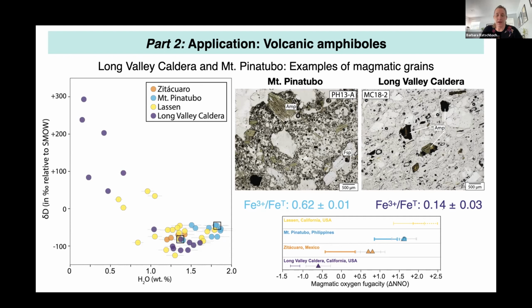So now when we, again, collect spectra, find a model, and get ferric overtone ratios, we can see that the Mount Pinatubo amphibole records a relatively high ferric overtone ratio of 0.62, versus the Long Valley amphibole records a relatively low ferric overtone ratio of 0.14. So this fits with our initial assumption that amphibole ferric overtone ratios are actually correlating with the oxidation state of the magma from which they crystallized.